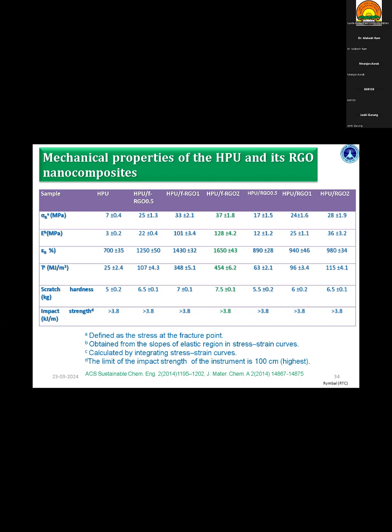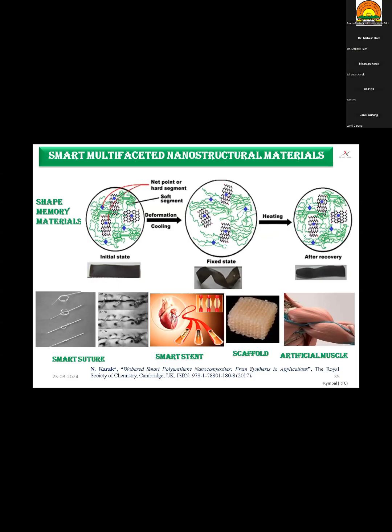All of you know, in most cases when you incorporate nanomaterial, because they are solid particulates, they reduce the elongation at break. But in our study, we have shown that elongation at break can also be enhanced significantly if you functionalize properly and if you incorporate this nanomaterial into the polymeric system by suitable modifications. And you can see from 700 to 1650% of elongation we have achieved just by 2% functionalized reduced graphene oxide incorporation.